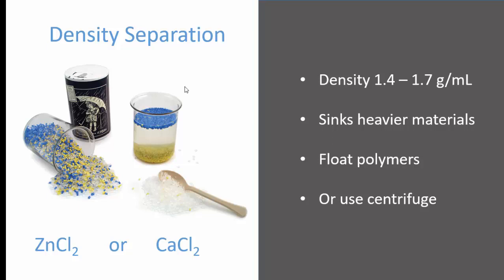One problem that we note with that is you'll see a lot of those plastic particles that float to the top want to adhere to the edge of the container, which can be problematic. And so for our studies, we chose to use a centrifuge rather than floating the material to the top. And I'll describe that briefly for you.